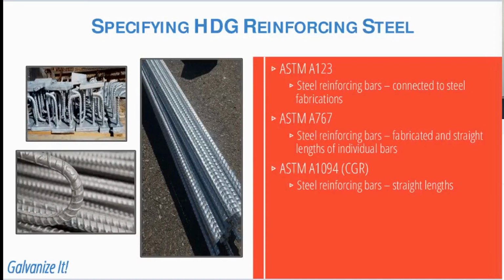ASTM A123, this covers rebar connected to steel fabrications or rebar fabrications. ASTM A767, this galvanizing standard covers the use of galvanized rebars in concrete. And then under this specification, rebars can be bent before or after galvanizing. But if bent before, it will stipulate minimum bend diameters to avoid embrittlement. And then ASTM A1094, this covers straight lengths of rebar with zinc applied in a continuous process prior to fabrication. And I'll go over the general requirements of each in the next few slides.